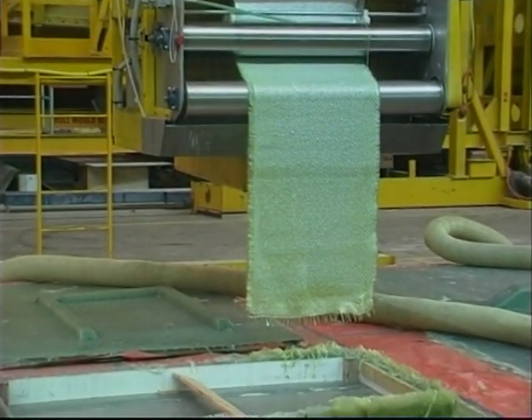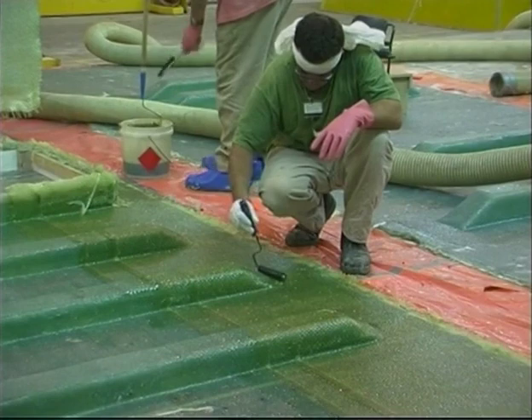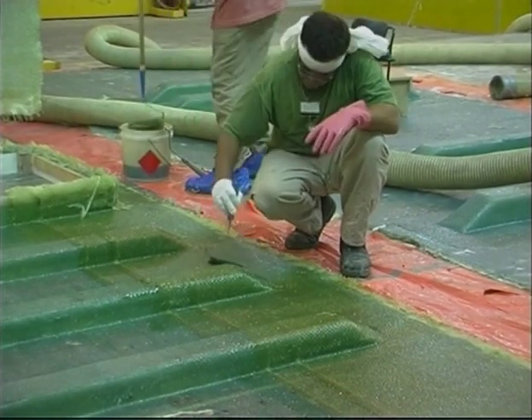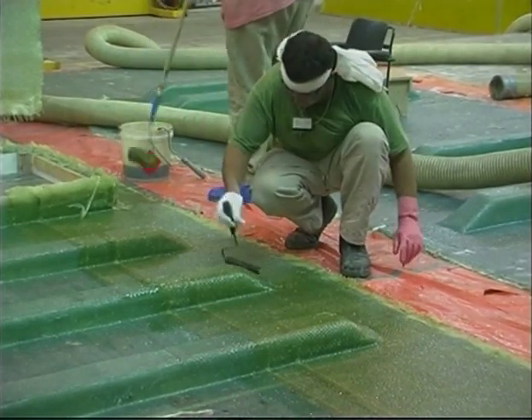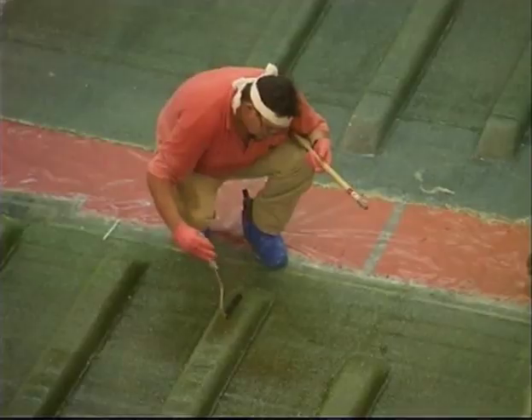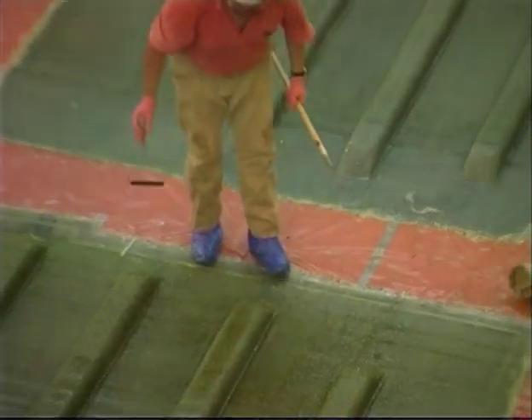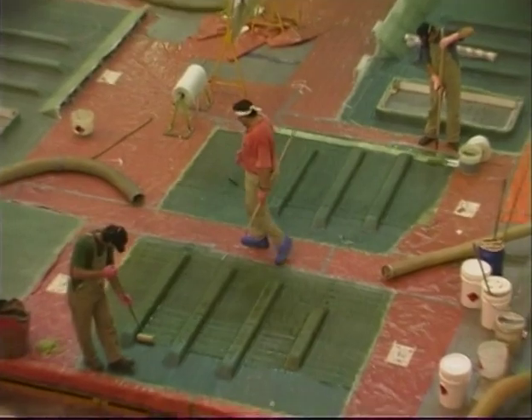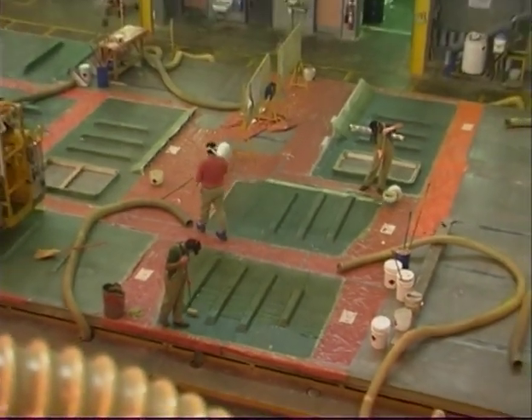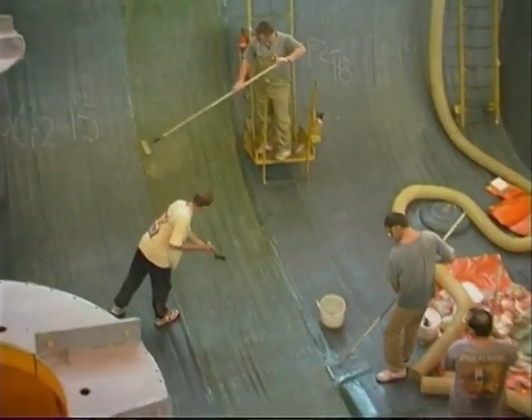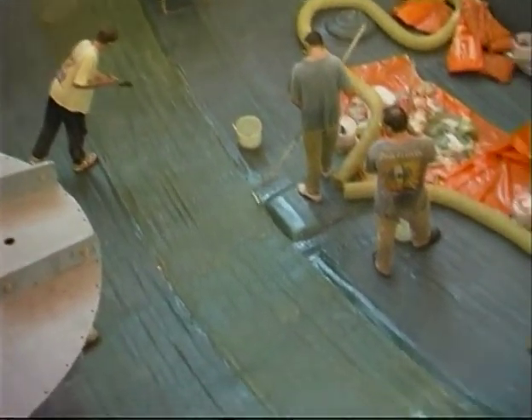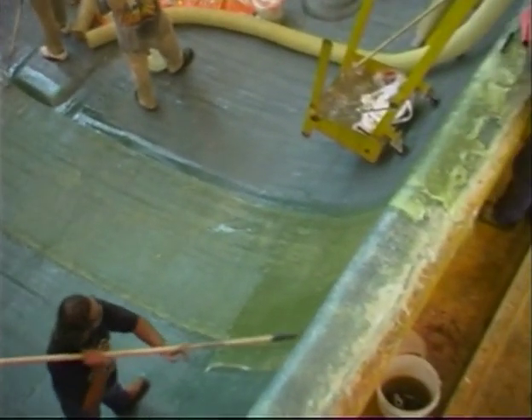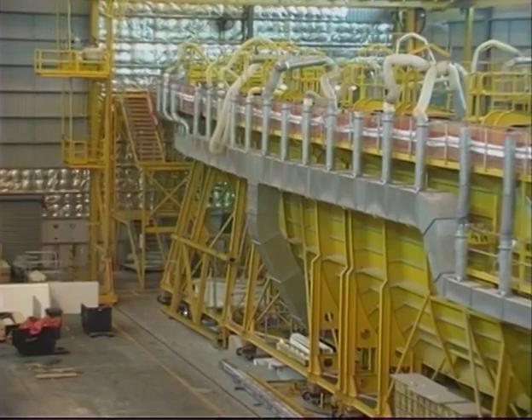One of the main advantages of composites is that the strength can be put just where it is needed. For example, the bottom of the hull is made up of 84 layers of woven rovings, giving a thickness of 160 millimeters. This reduces to a thickness of 50 millimeters topsides, made up of 28 layers. The glass to resin ratio is 1:1.